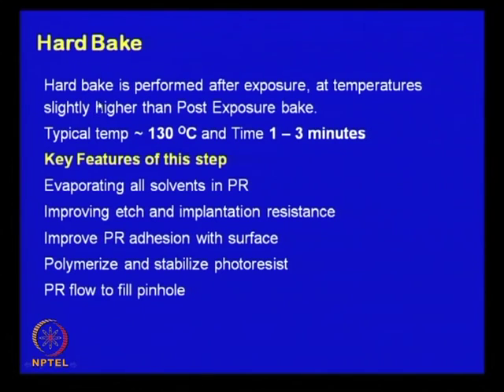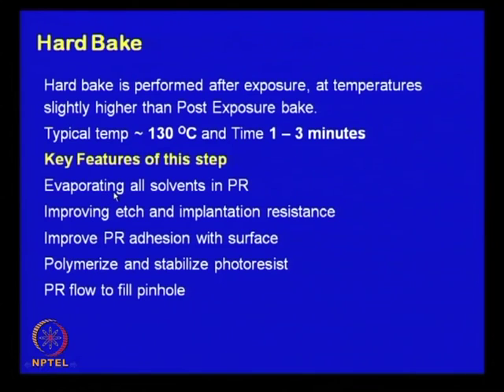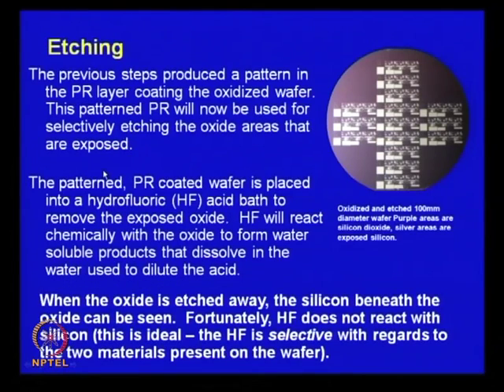Development is followed by hard bake, performed after exposure at a temperature slightly higher than the post-exposure bake — typically 130 to 150 degrees centigrade for roughly 1 to 3 minutes. The key features of this step are evaporating all solvents in the photoresist, improving etch and implantation resistance, improving photoresist adhesion with the surface, polymerizing and stabilizing the photoresist, and allowing photoresist flow to fill pin holes.